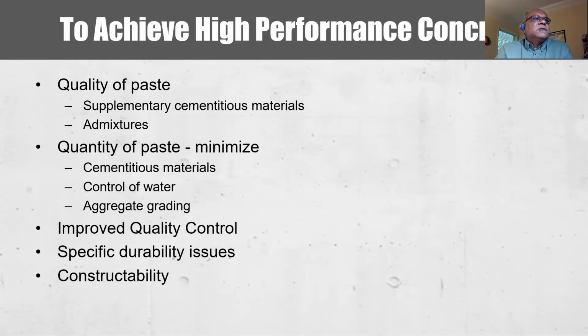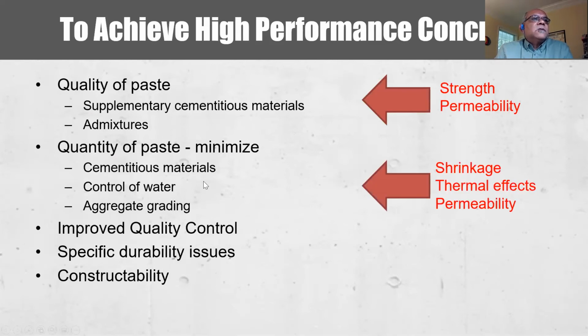To achieve high performance concrete, we want to look at the quality of paste, and we do this by the use of supplementary cementing materials. Those improve the quality of paste in terms of permeability. We use admixtures to reduce the water cement ratio. We try to minimize the quantity of paste by optimizing the quantity of cementitious material, good control on water, and optimizing the grading of the aggregates. So for strength and permeability, we depend on the quality of paste. For shrinkage, thermal effects, and permeability, we depend on the quantity of paste.